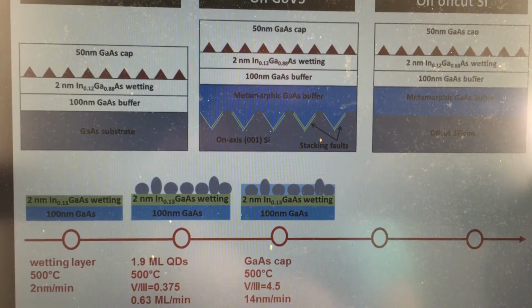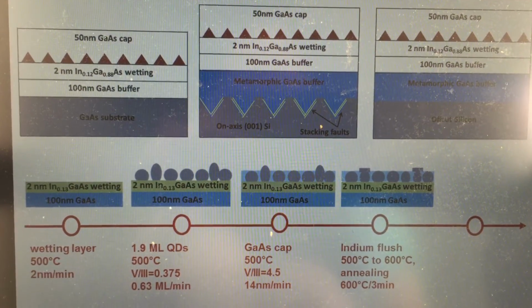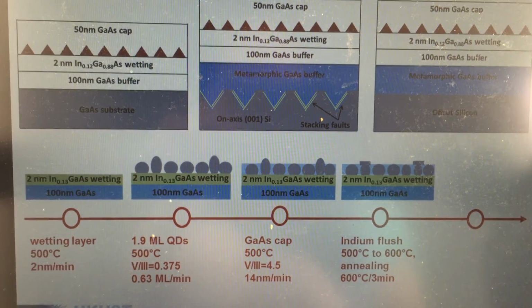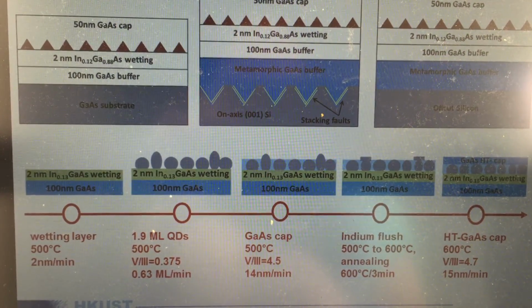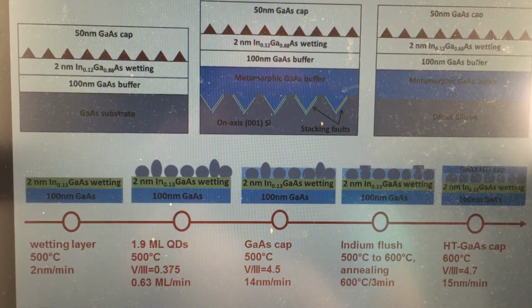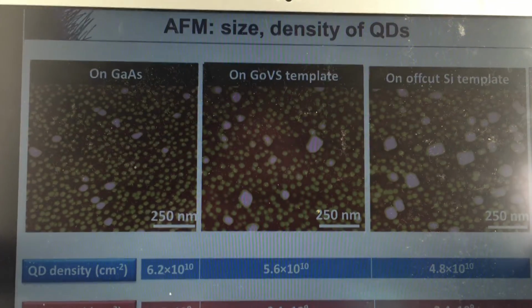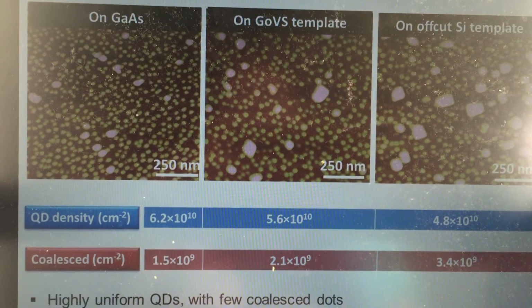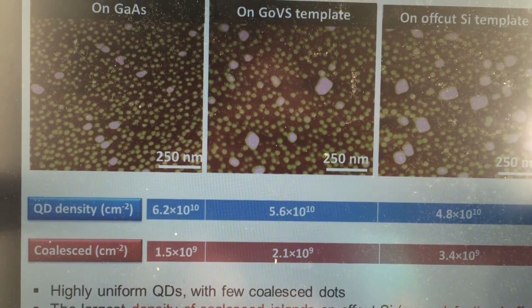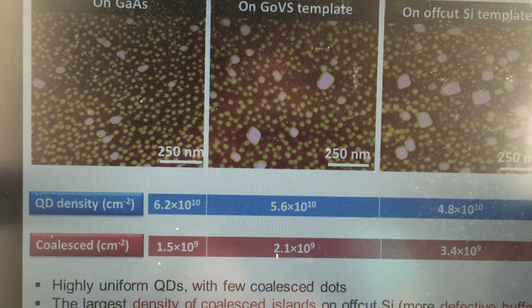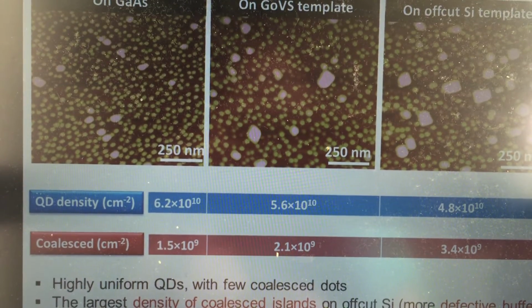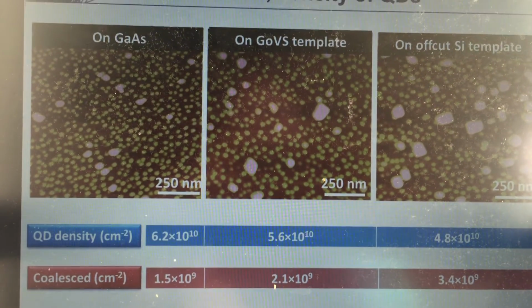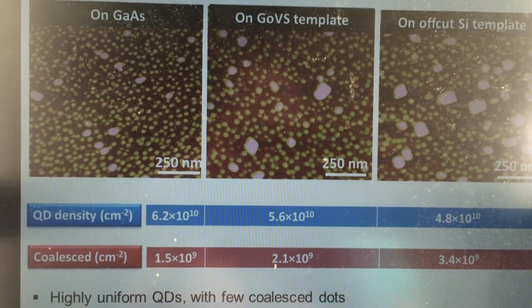After growing the GaAs cap, we then performed an indium flush to remove the large coalesced dots. And finally, we capped with another GaAs cap. Before the capping, the quantum dot structures were examined by AFM, and we find a high quantum dot density up to 5.6 times 10 to the power of 10 per centimeter square for the quantum dot on GoVS template.